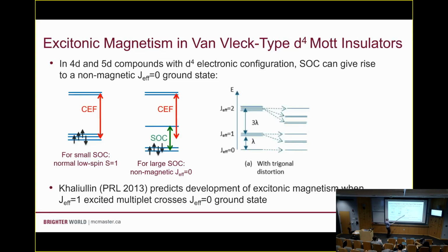If you imagine looking at the J effective non-magnetic ground state here, the first excited state is this manifold, a triplet of J effective 1 states, then a quintet of J effective 2 up here. And if we can bring the J effective 1 state energy down so that it crosses the energy of the J effective 0 state here, then this can condense and we get excitonic magnetic order. So you can do this with structural distortions. That's one way to bring these energy levels down.